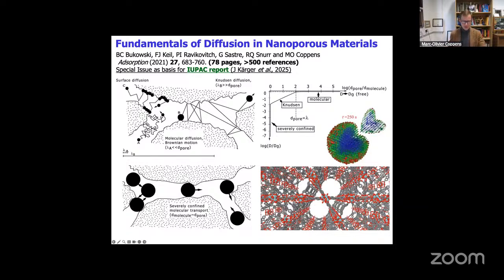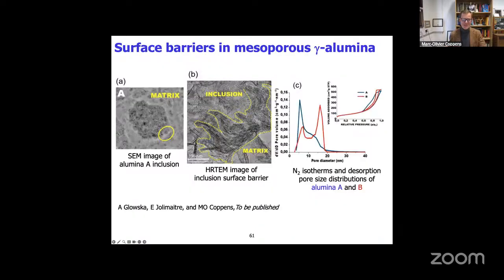And what I tried to show you here is that even for mesoporous materials, you have some exciting things happening, and that has not been studied as far as I know. So that there are these types of effects. And just like Jeroen Denayer, Gino Baron, Jörg Kärger, and colleagues demonstrated a number of years ago, if you start to look at a bag of zeolite crystals and you take out different individual crystals, you find that the transport properties are different. The uptake is different due to surface barriers. And we have also shown how you can modify these surface barriers in our work. So it becomes really important. But earlier work, while skin effects were even proposed by Kärger and also by Barrer in the 1980s, there was no way of directly measuring that until now.